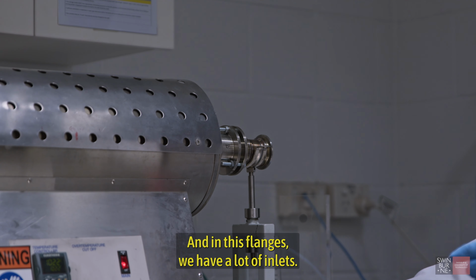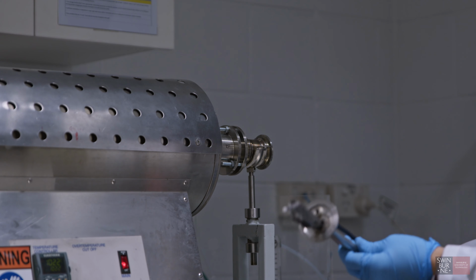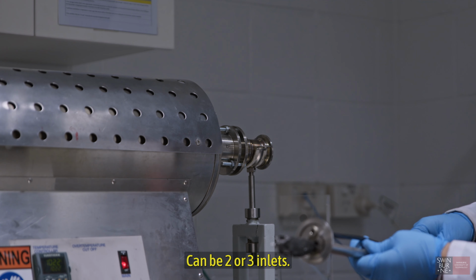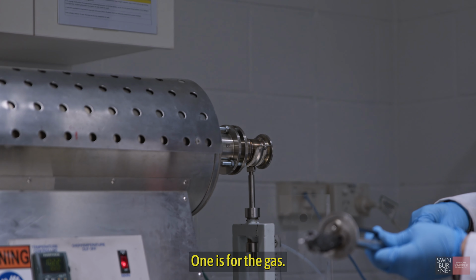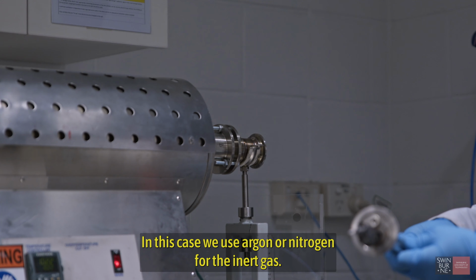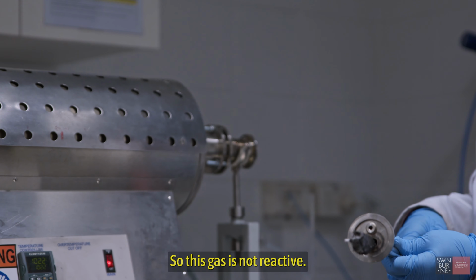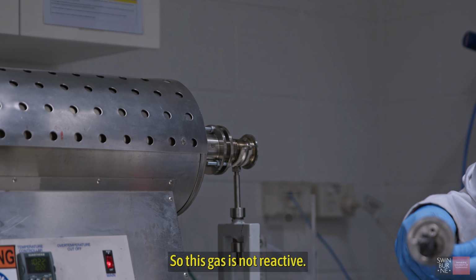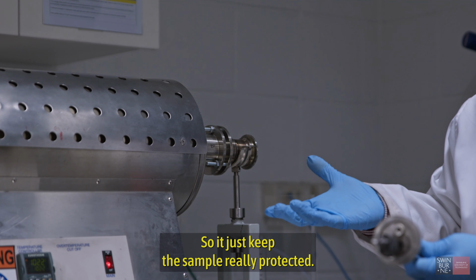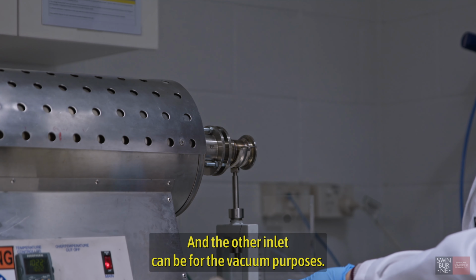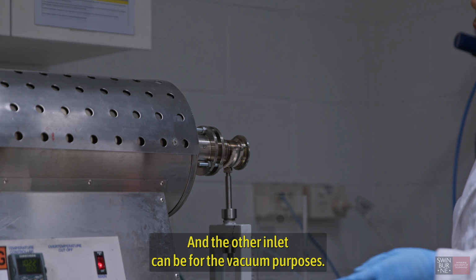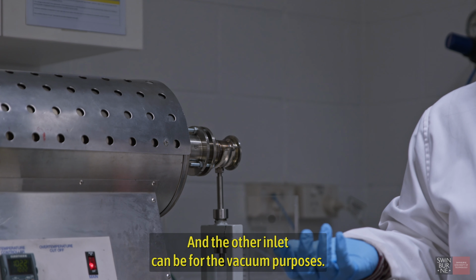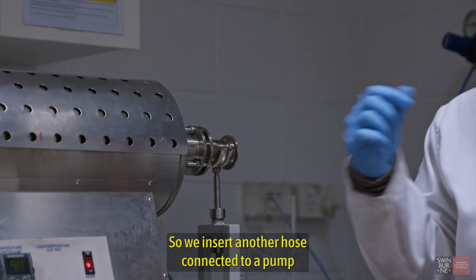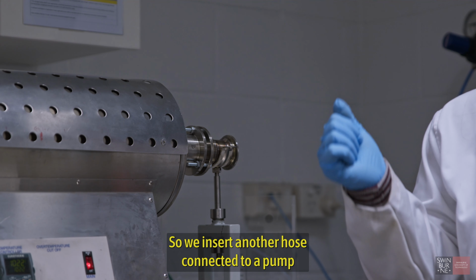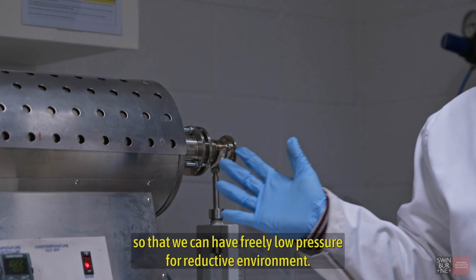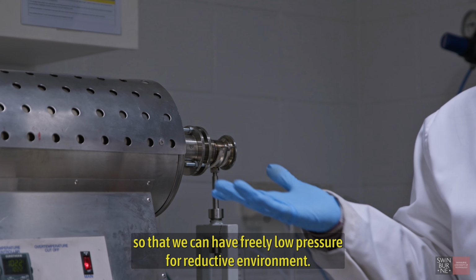And in these flanges, we have a lot of inlets. Can be 2 or 3 inlets. One is for the gas. In this case, we use argon or nitrogen as the inert gas. This gas is not reactive, so it just keeps the sample really protected. And the other inlet can be for vacuum purposes. So we insert another hose connected to a pump so that we can have really low pressure for a reductive environment.